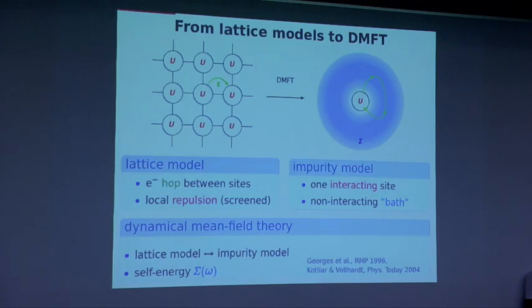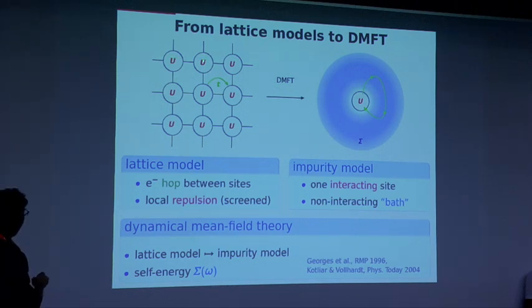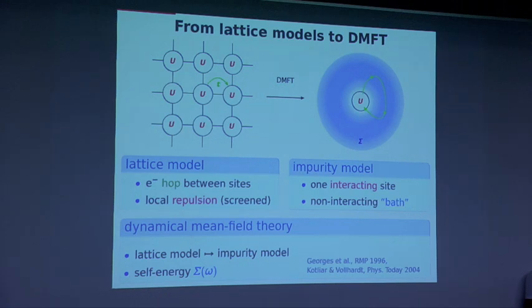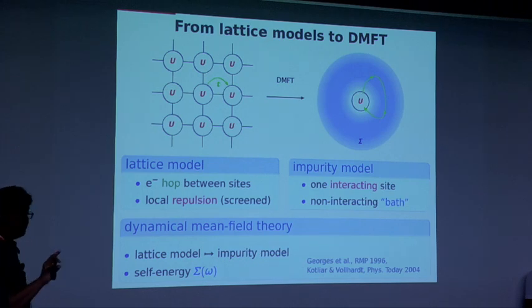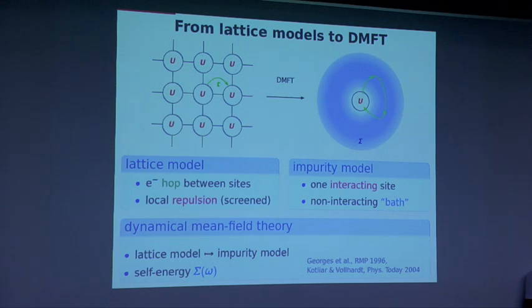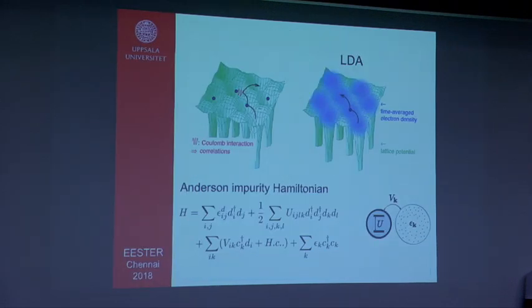So basically, what is the principle, in a few words? The principle is that you have a lattice model where you have all sites which have a Coulomb repulsion associated with them, and an electron is trying to hop from one site to the other. So this is an infinite lattice. The idea of dynamical mean field theory is to map this infinite lattice to an effective impurity model, where you have one impurity embedded in a surrounding which we call a bath. So the electron is getting constantly exchanged between this impurity site and the bath states like this. And the self-energy actually describes these bath states. It's very simple words actually. So a lattice model mapped into an impurity model, and we have the self-energy, which has an omega dependence that we need to calculate.